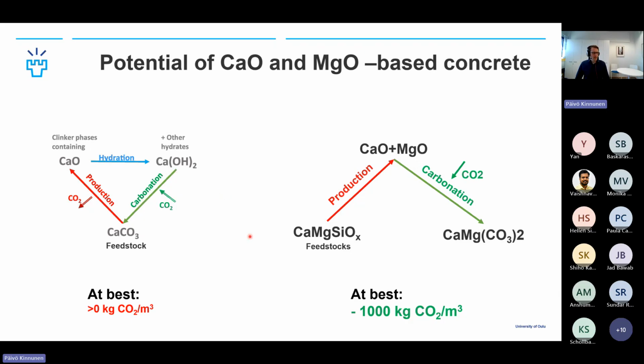But this is inviting us to think in a slightly different way, which is that if we start from calcium magnesium silicate feedstocks, and then we produce calcium oxide and magnesium oxide, we need energy, but not CO2. We don't emit CO2 from the chemistry perspective. And then we can do carbonation, and then we could end up with the calcium and magnesium carbonate, basically dolomite. And at best, we could there reach something like minus 1,000 kilograms of CO2 per cubic meter. So this is just in theory, but you can see that there's a big difference, and the question is, is that possible?